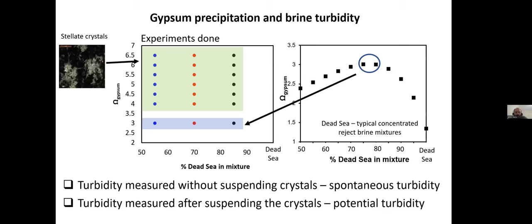This specific oversaturation is important because if we look at the graph at the right that shows the oversaturation as a function of Dead Sea to reject brine mixtures, this is the maximum oversaturation it could get if I exclude, just by mixing. It means I exclude other processes that could concentrate the brine, like evaporation, that take place in the natural system, but only by mixing, this would be the maximum expected oversaturation we could get. I also did experiments closer to equilibrium, but their results were pretty much insignificant, so I'm not going to discuss them. And with these brines, I did two sets of experiments.